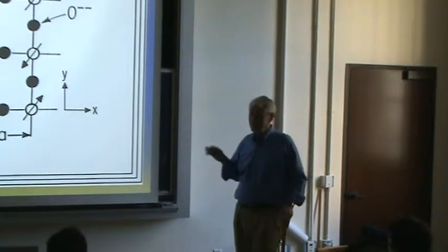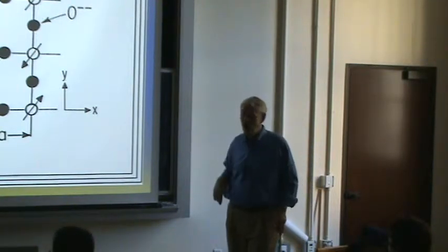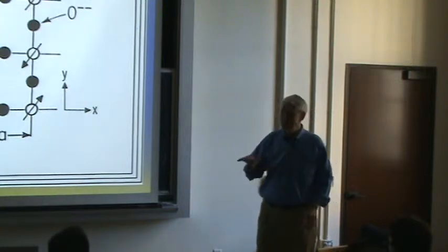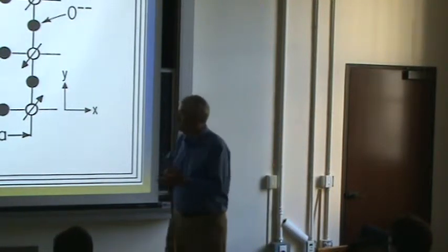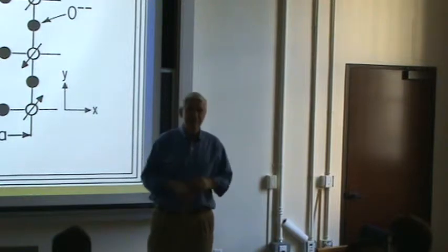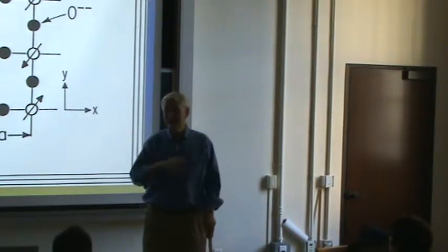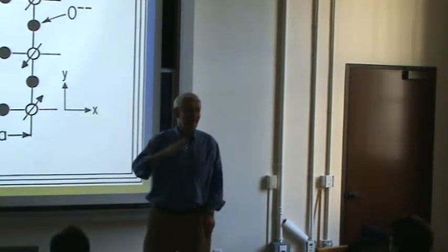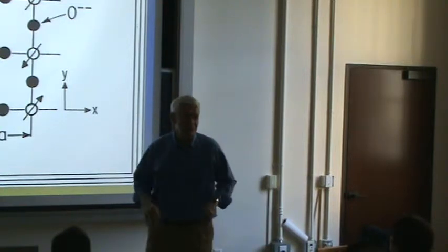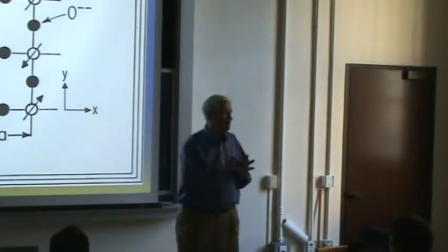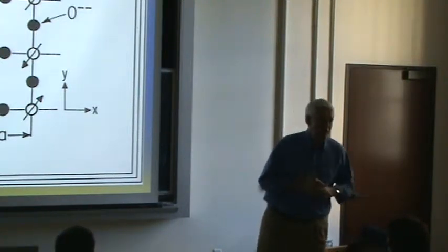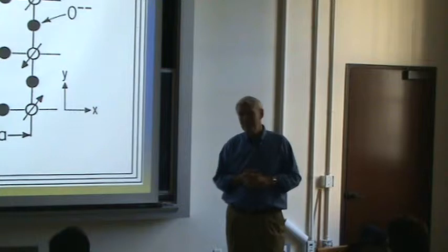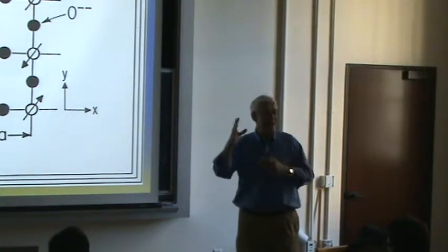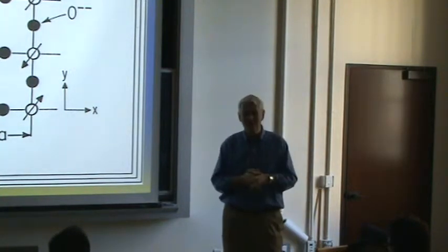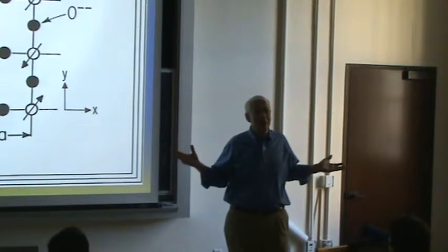In addition, Marc Kastner, down the hall, and I had worked together on some materials which, 15 years later, became fashionable: magnetic oxides that exhibit giant magnetoresistance, so-called lanthanum manganese oxide materials. So we had done a lot of work on these oxides, which we never published. I regret it, since it became very fashionable later. We did a number of the basic measurements in the lab. We didn't publish because we just couldn't figure out what it meant.